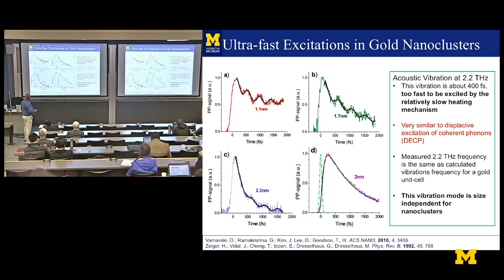That's typical. So here's the typical case. You have a big particle. Down here, it's this purple, okay? And as you wait a very long time, you'll see what we just saw before, it just decays. That's nice. But as you make this particle smaller, something interesting happened. So for the case of the 102, I think, cluster, you started to see these kinds of oscillations. And then for the 55, you see the oscillations again. And then by the time you get to the 25, the oscillations are very strong.